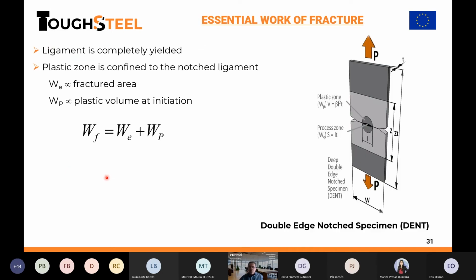How does it work? Let's look at this specimen. It is a double edge notch specimen in tension, called DENT. Two notches on the edge, tensile loading. If the area between the two notches is completely yielded, and the plastic zone is confined, I mean, we don't have plastic zones around the specimen, we can effectively separate the total fracture work into the energy for fracture plus the energy for plastic deformation.